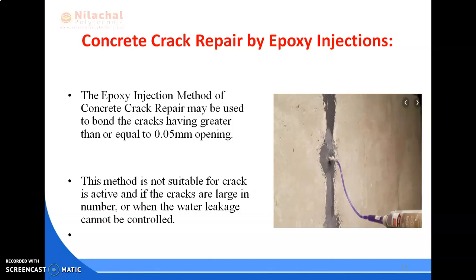In the epoxy injection method, cracks on exposed concrete surfaces are sealed by injecting epoxy under pressure into the crack. This method requires a lot of discipline and a skillful person executing the repairs. Epoxy resin loses strength when exposed to fire or sustained elevated temperatures, so fireproofing protection is required for such structural repairs.